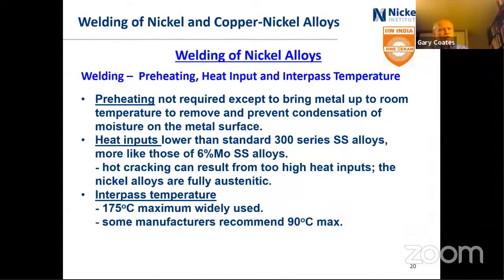Typical heat inputs for most of the nickel alloys are lower than the standard 300 series stainless steels, more like the 6% molybdenum stainless steels. The nickel alloys are fully austenitic. The filler metals are fully austenitic, and hot cracking can result if you have too high heat inputs. And we'll come back to that shortly when we talk about processes too.